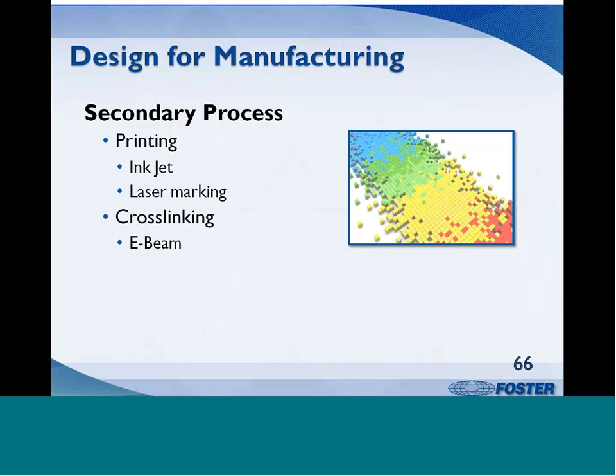Cross-linking can be encouraged by adding in a co-agent that will co-cross-link with the base resin during electron beam processing of a part. This will allow the part to behave as if it were formed from a thermoset resin while keeping the fabrication flexibility of a thermoplastic.